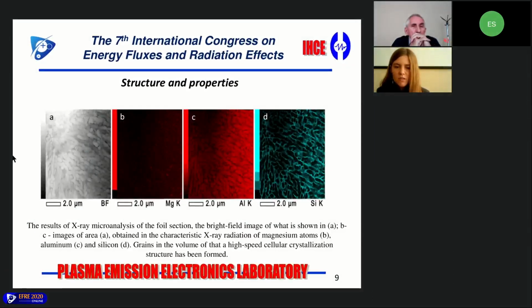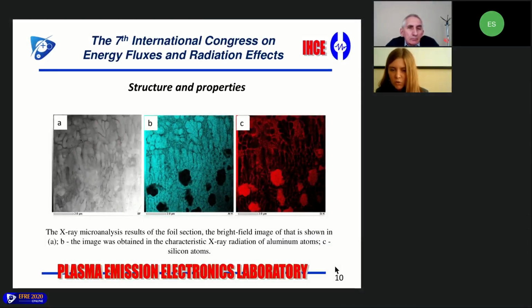Using the method of transmission electron microscopy, it was found that a structure of high-speed cellular crystallization is formed. Firstly, there are grains in the volume of which a structure of high-speed cellular crystallization is formed. You can see here. And second, there are grains in the volume of which, along with the structure of high-speed crystallization, crystallites of excess globular silicon are present.